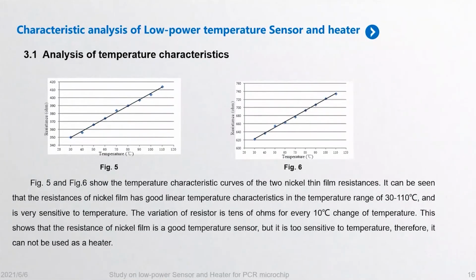Figure 5 and Figure 6 show the temperature characteristic curves of two nickel thin film resistances. It can be seen that the resistance of nickel film has good linear temperature characteristics in the temperature range of 30 to 110 degrees centigrade and is very sensitive to temperature. The variation of resistor is tens of ohms for every 10-degree change of temperature. This shows that the resistance of nickel film is a good temperature sensor, but it is too sensitive to temperature, therefore it cannot be used as a heater.